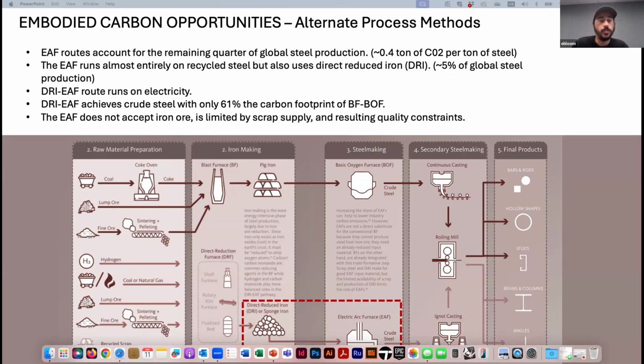And if you were to pair direct reduced iron with the electric arc furnace, it can achieve crude steel with just 60% the carbon footprint of traditional steel making. If you were to use hydrogen as a clean energy carrier for the direct reduced iron equipment and use that alongside the electric arc furnace, it can come down close to net zero emissions. And so on paper, the electric arc furnace seems like the way to go, and very promising, but the reason why its use is so limited is because it can't accept iron ore as a main input. I'll talk more about the reason on the next slide, but because it can't accept iron ore and it depends on steel scrap, there is limited availability of steel scrap. And steel scrap often produces a lower quality grade steel.